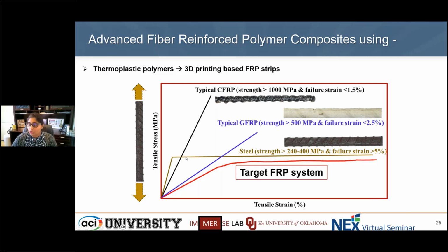But the strength, even though nominal for, let's say, a mild steel, we have a very good failure strain of above 5%, which makes it really ductile and great for civil infrastructure. If we look at CFRP and GFRP, we have, of course, very linear elastic behavior for high strength composites. And so I'm strictly talking about unidirectional, where the fibers are going only in one direction, preferably in line to the tensile load. We have low ductility, so more linear elastic to failure, brittle, abrupt, and broom-like. The strength, of course, is very high for CFRP, lower strength for GFRP, but a little higher in strain.